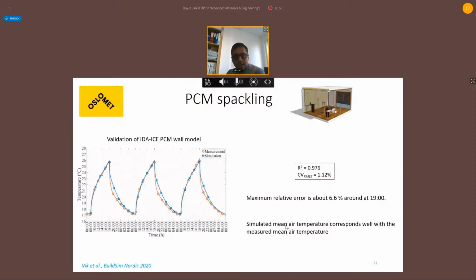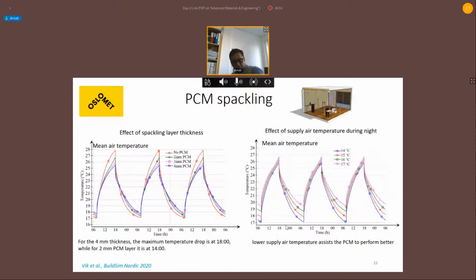And we see here the effects of this thickness, as well as the supply air temperature at night and the supply airflow rate at night. So what we see here is you cannot keep on putting phase change materials so that you gain benefit. It means one could go to an optimum level because it has to be recharged. So what we see here is the drop in temperature in daytime, which is the red with no PCM, and increasing PCM thickness. So you see this dropping, but it is becoming non-linear. So the reduction is becoming less.